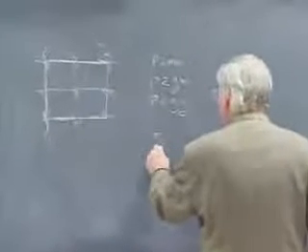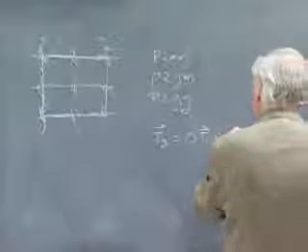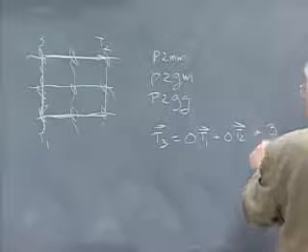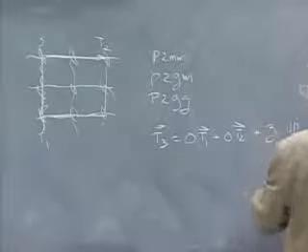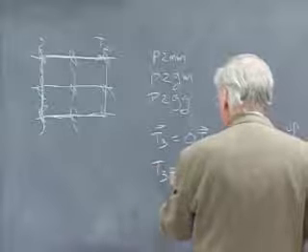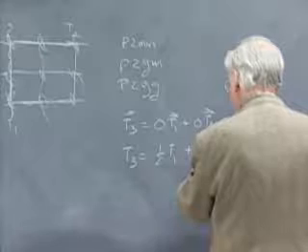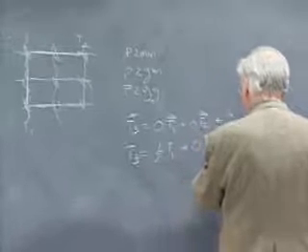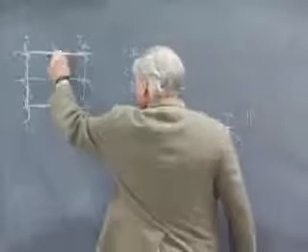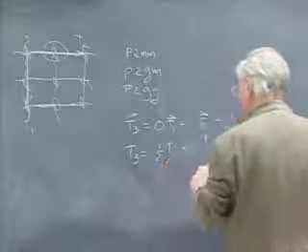So T3 could be 0 T1 plus 0 T2 plus some amount Z, which is straight up. Or it could be equal to 1/2 of T1, 0 T2 plus Z. That would be making the origin twofold axis fall over this location.